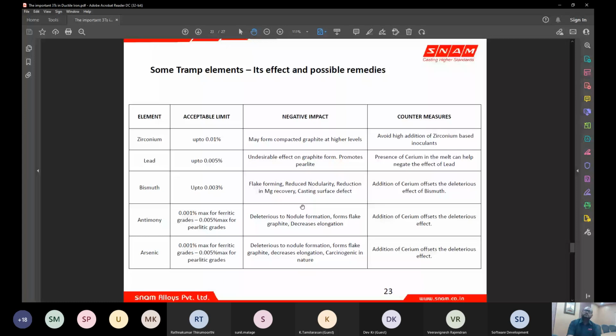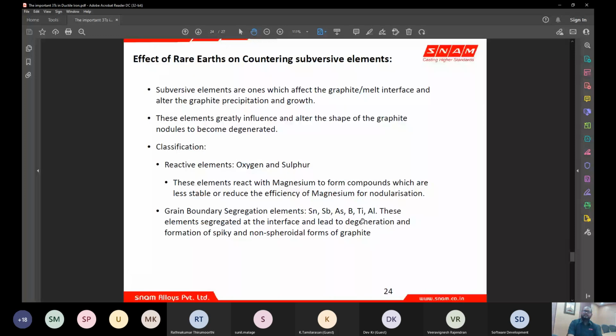So what do rare earths do? Rare earth reacts with oxygen and sulfur. Rare earths react with grain boundary elements, which are the tramp elements which we had discussed previously. Antimony, arsenic, bismuth, boron, titanium, and all. It forms some compounds which do not segregate in the grain boundary, such that you don't get any grain boundary carbides. So these are some of the compounds which lanthanum and cerium and other